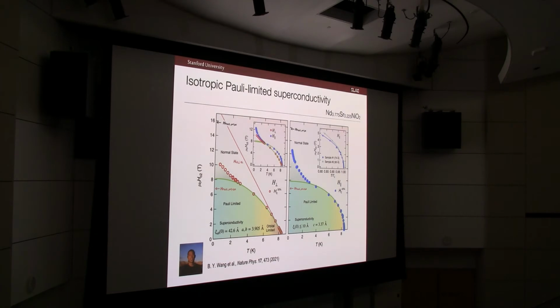And the final basic story I can tell you about the superconducting properties, slightly different compound, but don't worry about that, is looking at the resistive upper critical field. You don't need to worry about all the details here, and this is basically just to say that if you look at suppressing superconductivity by a perpendicular magnetic field, so perpendicular to the plane, or in the plane direction, parallel, what's surprising is that the HC2, the upper critical field, is basically isotropic. We don't know of any other layered oxide superconductors that have that. Usually it reflects the anisotropy of the electronic and crystal structure.